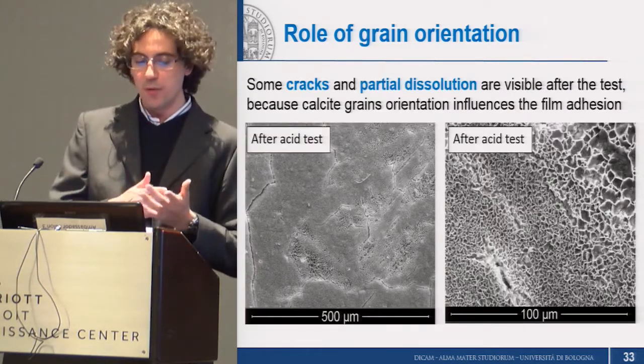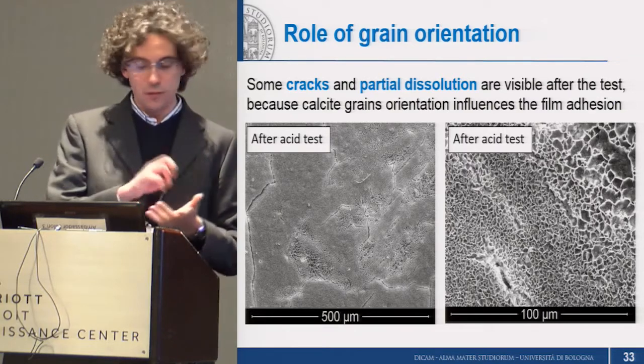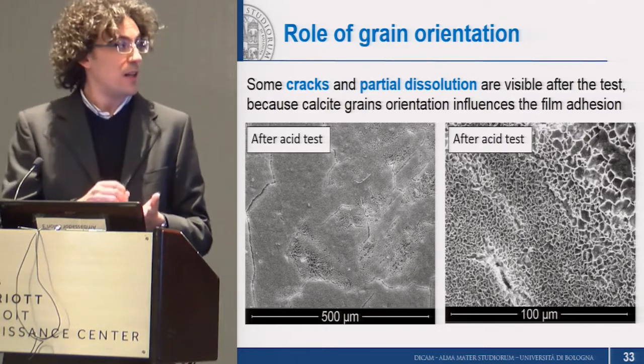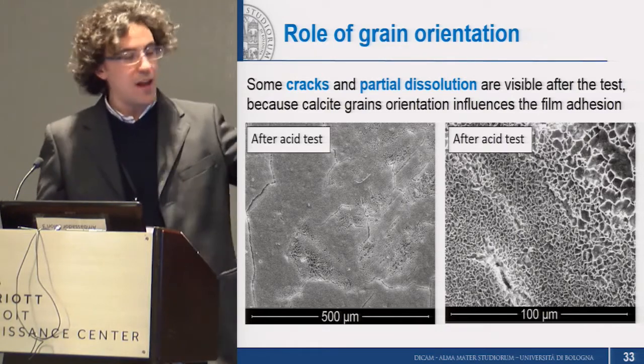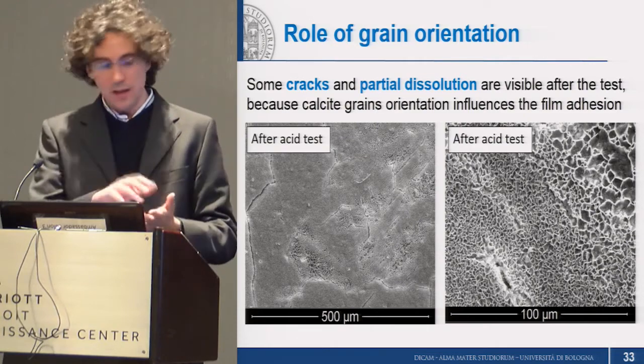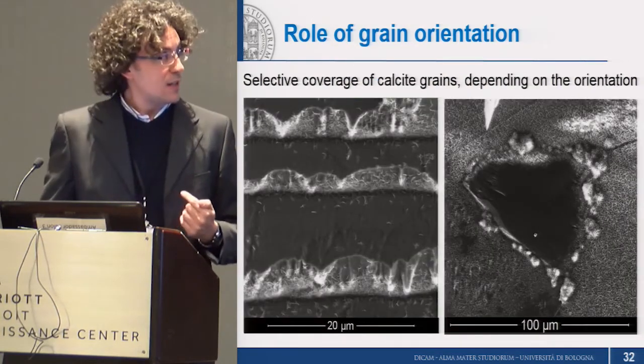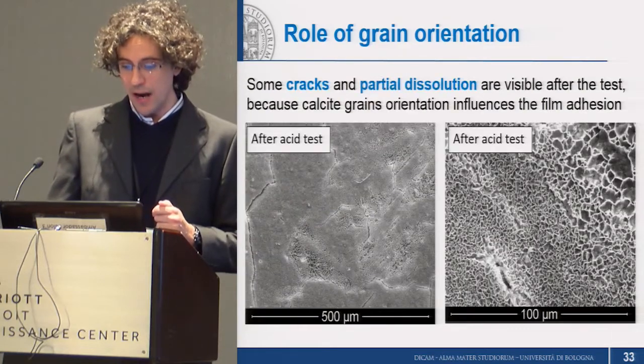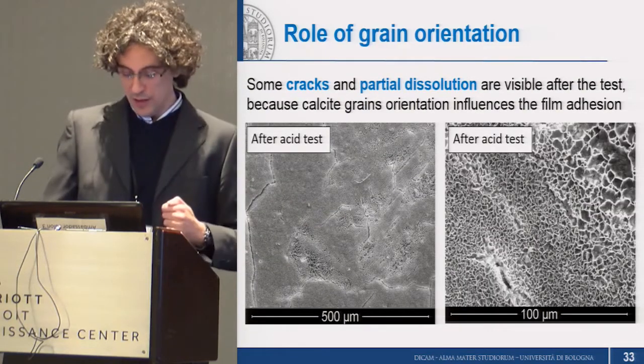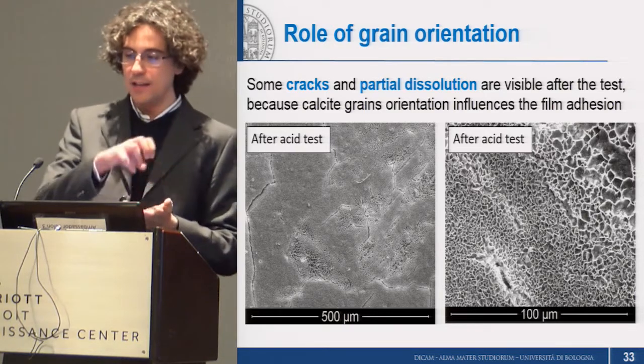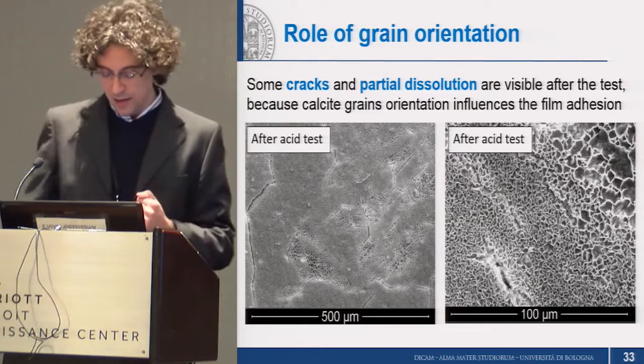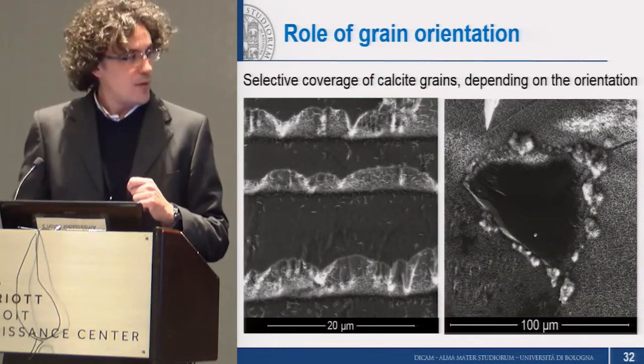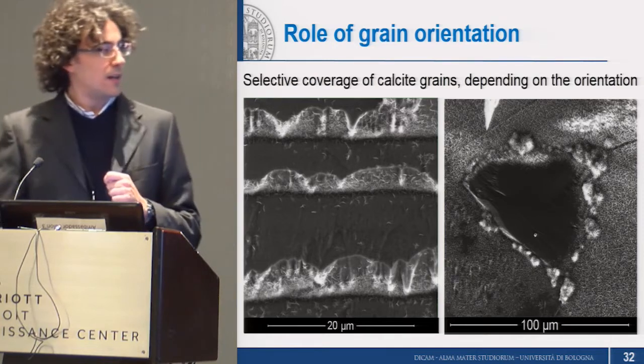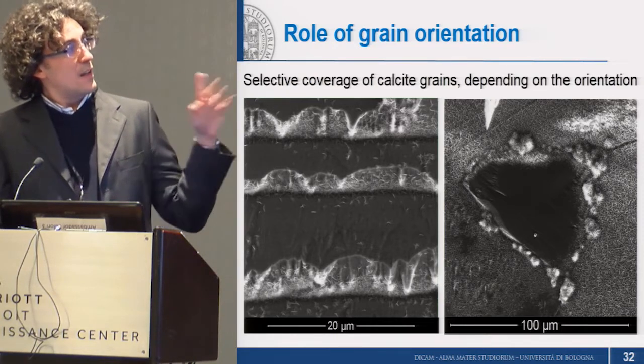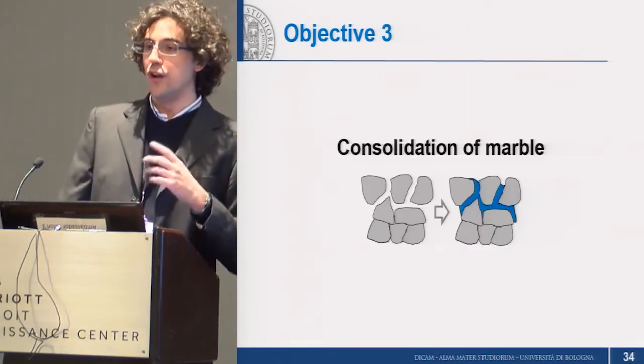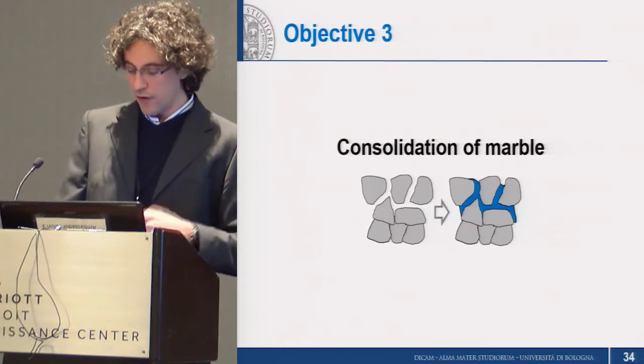And this is why, if we observe our coatings after the acid attack test, we can see that the acid was able to produce some microcracks, and in some cases to worsen our treatment. And this is because, starting from these bare areas, the acid is able to reach the marble and then act at the interface between the substrate and marble. So we are currently working on this to improve the ability to cover grains, to nucleate hydroxyapatite also on calcite grains with the least favorable orientation, and we hope that by screening additional solvents, we will be able to improve this part.